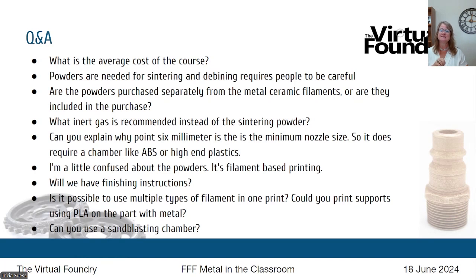But you're burying your print in a refractory ballast material. For copper and bronze, it's Al2O3 or aluminum oxide. And that material then provides part shape support as you go through the debinding process. Then when you're getting ready for the sintering process, you'll pack your print in magnesium silicate, which provides part shape support, but also easily moves out of the way as your part shrinks on itself during the sintering process. And then during sintering, you're also applying sintering carbon to the top. So that's where the powders come in. It's in that debind and sintering process, and they're used to support your part shape and mitigate oxygen.